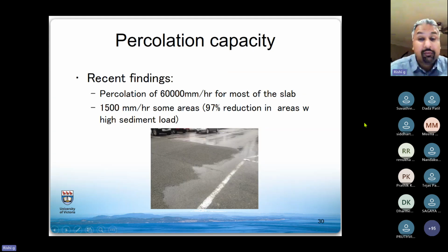So we started off with a very, very high percolation capacity. I don't think we needed that much percolation capacity, but it ended up giving us a little bit of a buffer because we knew that the percolation capacity will reduce over a period of time due to the stormwater contaminants that come with it. Just a visual here at the bottom. So remember I said the percolation, the spot was on the downstream side. You see a lot of rainwater is coming from the upstream. It hits the porous concrete patch, and by the time it crosses about 3/4 of the test pavement, everything is actually absorbed within the stormwater.